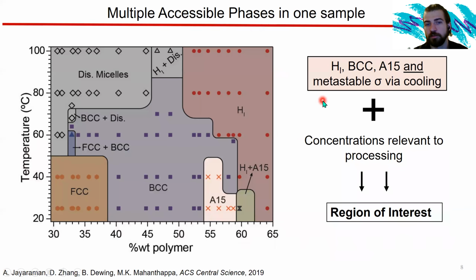What you don't see on this is that the authors reported that in this window, when you cool from hexagonal cylinders down, there's a Frank-Kasper sigma phase that's accessible via a thermal annealing procedure. Now, in addition to this complicated phase behavior on the path to equilibrium, you have concentrations that are relevant to processing, and so this is a region of interest for us to explore, so we understand how to work with these materials and get the phase behavior and the properties we want.